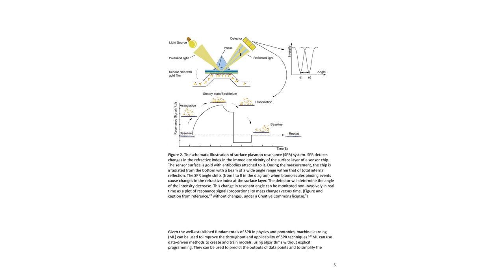A typical experiment, as illustrated in the paper, might involve a sensor chip coated with gold, onto which antibodies are attached. When a sample containing the target biomolecule is introduced, these molecules bind to the antibodies. This binding event adds mass to the surface, changes the local refractive index, and causes the SPR angle to shift. A detector monitors the reflected light and tracks this change in the resonant angle over time. The resulting plot, often called a sensorgram, shows the association of the molecules binding, a steady-state equilibrium, and then the dissociation as the molecules unbind. This allows for non-invasive, real-time monitoring of molecular interactions.